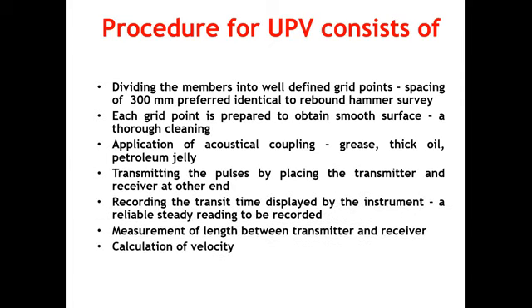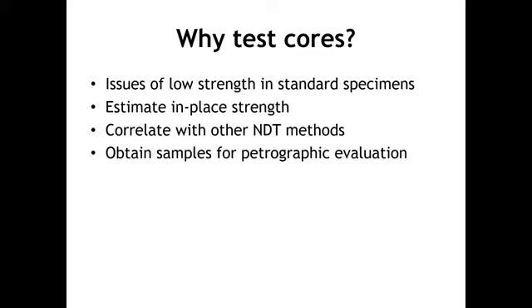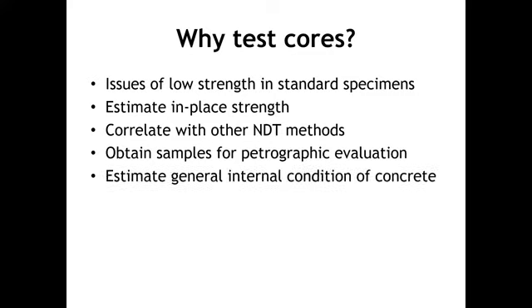And sometimes you use this for doing the petrographic evaluation, because now you get aggregates which are more reactive. Then we need to be very careful, otherwise alkali aggregate reaction issues will come. You estimate the general and internal condition of the concrete, and then get information about the carbonation depth, density, and so on. For those, we use this code.